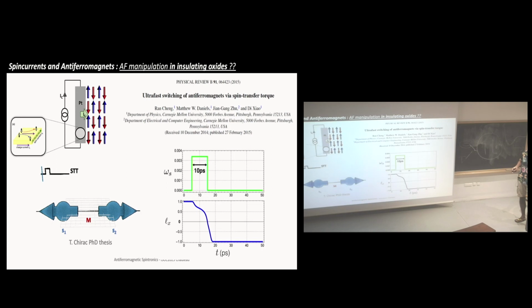So what's happening in oxide? Okay, in oxide it is not so easy. So first of all, when it's not so easy, we do a bit of simulation and theory. But definitely, what will happen is exactly what's happening here. When you have the spin torque, then the sublattices will start canting, okay? And when they cant like this, then you create a huge exchange field here. And then this exchange field will take over, and the spin will start precessing around this exchange field.